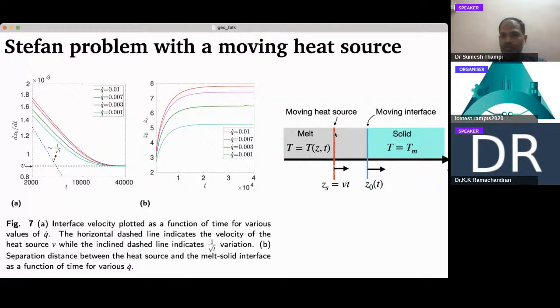If the heat source was not moving, this would have continued to go down forever. But what happens is that when this comes down, at some point the velocity of the interface becomes equal to the velocity of the heat source. Once they become equal, then the velocity of the interface doesn't change anymore. You can see that once the velocity reduces and becomes equal to this dash line, where the dash line corresponds to the velocity of the heat source, it becomes a constant and it stays there. So that is as if the heat source is moving to the right, and that heat source will continuously push this interface to the right, but with the same velocity. And when two things are moving with the same velocity, the distance between them cannot change. Therefore that continues to be a steady state solution.